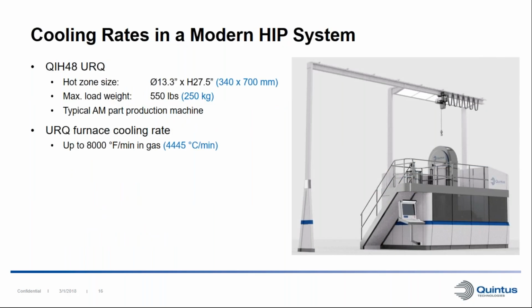So I want to give you an example of actual absolute values of cooling rates in a modern HIP system. If we take our QIH48 URQ here as an example, it has a hot zone size of just above 13 inches diameter, and almost 30 inches high. The maximum load weight that we can process in this kind of HIP is 550 pounds. And it's a typical size for a production machine for additive manufacturing parts.